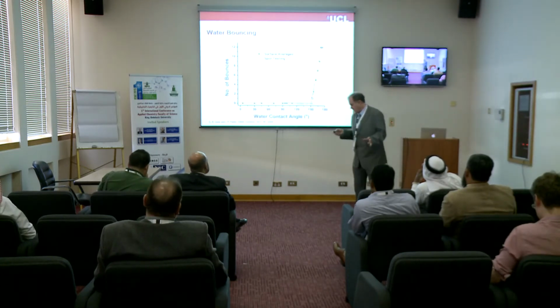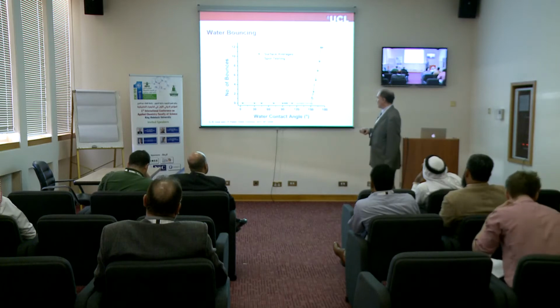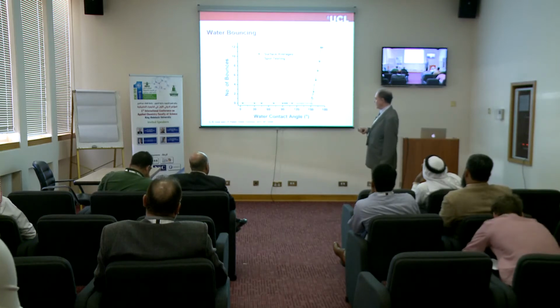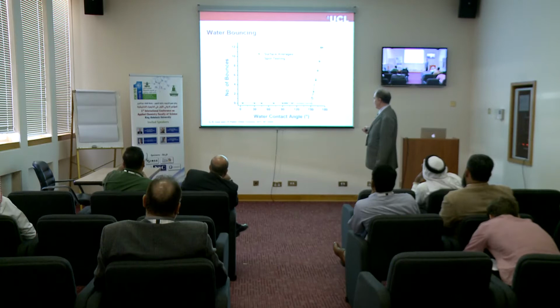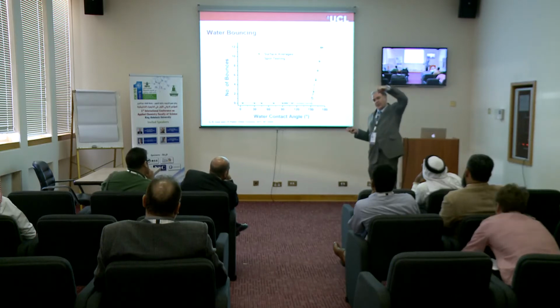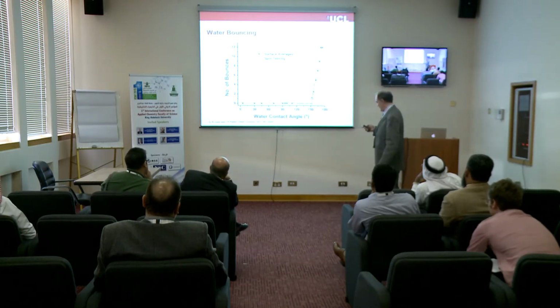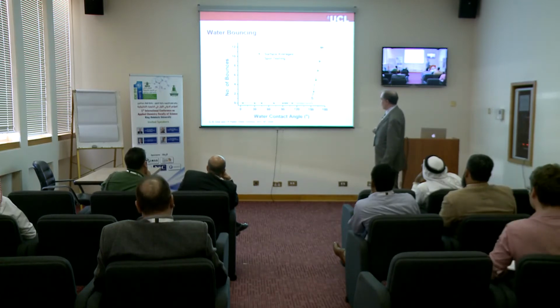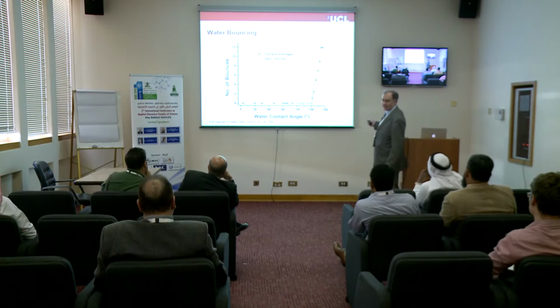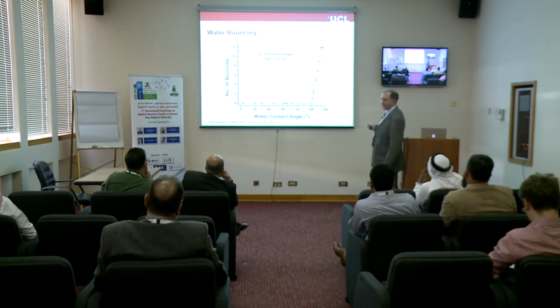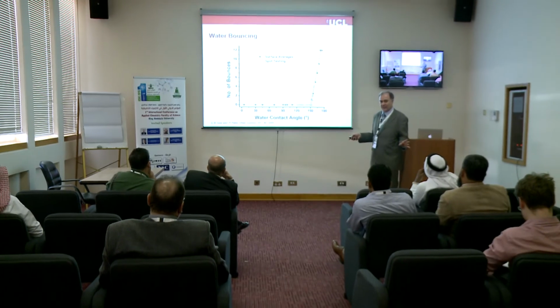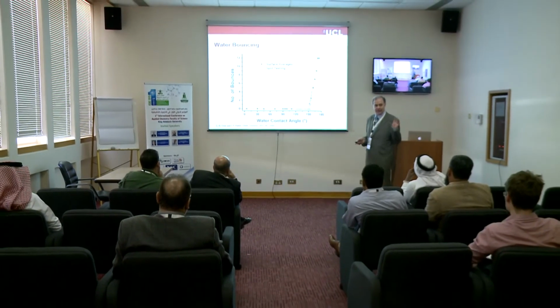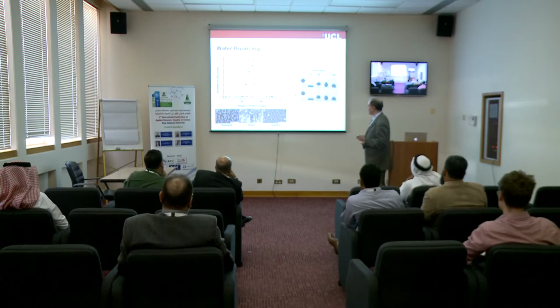Now this is something which we discovered, we published in ChemComm a few years ago, is that if you look at the static water contact angle and then you drop the water from a height from the surface, we found a linear relationship. As soon as you hit the super hydrophobic mark, the water starts bouncing on the surface. And the more super hydrophobic the film, the greater the number of bounces that you will see on the surface. Now this is important for self-cleaning applications.